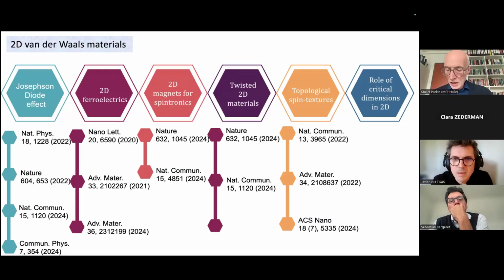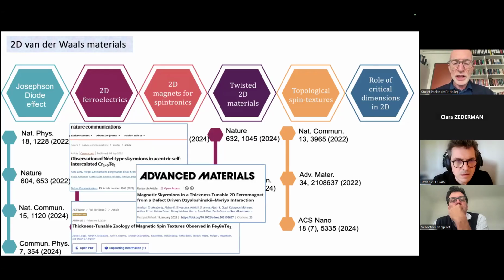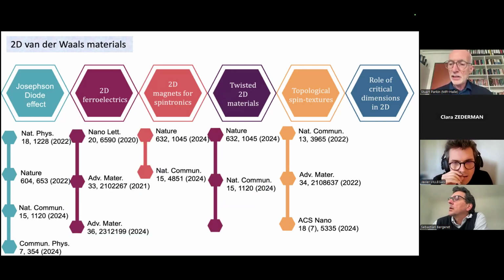Okay, so finally, these 2D materials show extraordinarily interesting topological spin textures, including skyrmions, a wide range of topological structures. In many cases, we've shown that the 2D systems, which are nominally centrosymmetric, have broken symmetries, which allow for the presence of these skyrmions. And those broken symmetries arise from defects in the 2D systems. And this is very, very interesting.